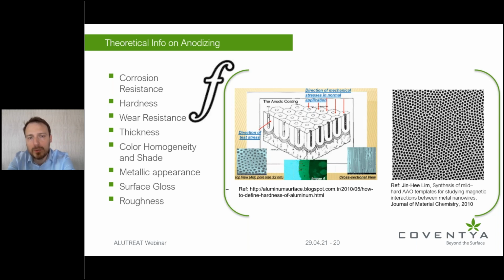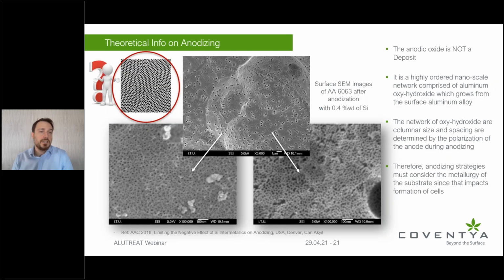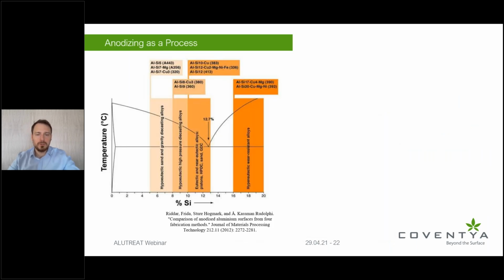If you go online and Google anodizing, you end up with pictures of a beautifully structured honeycomb-like layer structure, but these are possible to obtain only under very specific circumstances, which means in a small beaker on very pure aluminum. Generally speaking, in normal life, you end up with a more chaotic layer like this, where problems occur due to this inhomogeneity, like seal quality, hardness, or even the color. So it is very important to control the process, because in real life, like we have shortly mentioned, we do not have pure aluminum because of physical strength needs.